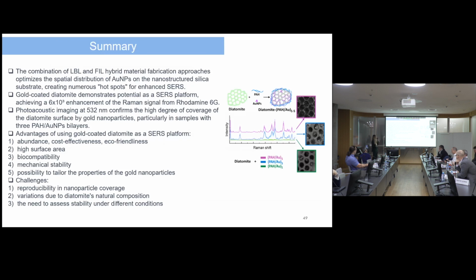Before I come to the disadvantages, the summary of this whole part is that the combination of layer by layer and freezing-induced loading method optimizes the spatial distribution of gold nanoparticles on the silica substrate. It creates numerous hotspots for enhanced SERS. The enhancement factor achieved was calculated to be 6,000. Photoacoustic imaging confirms the high degree of coverage of the diatomite surface by gold nanoparticles in samples with 3 and 5 bilayers. The advantages of potentially using this platform as a SERS substrate: